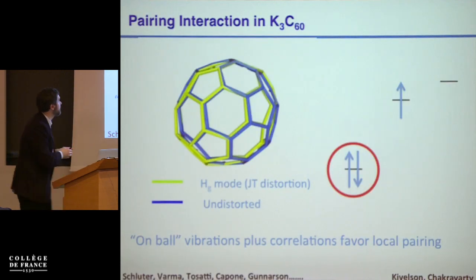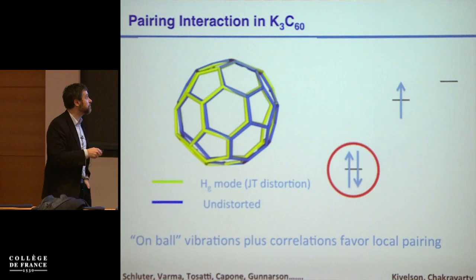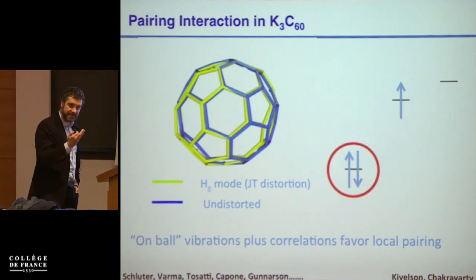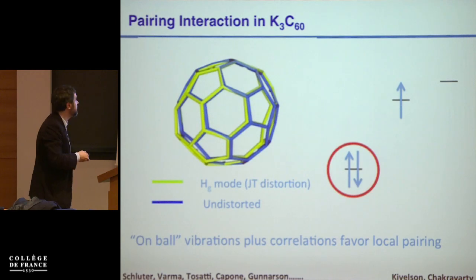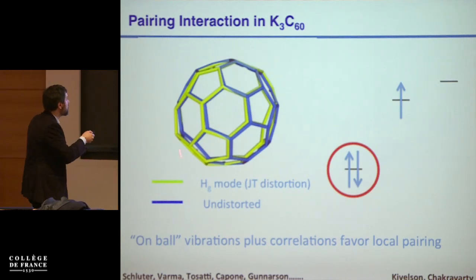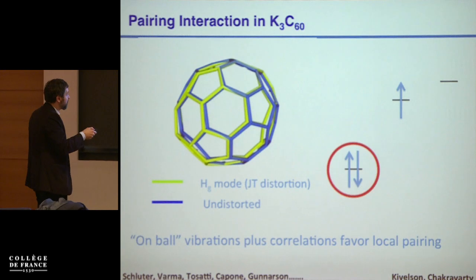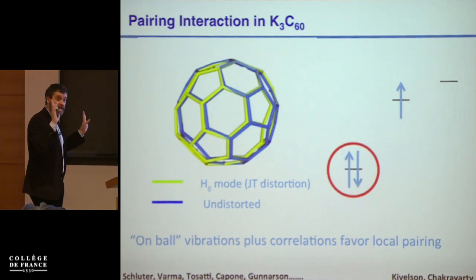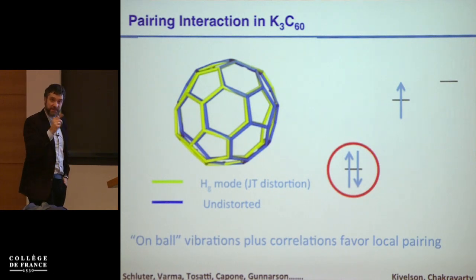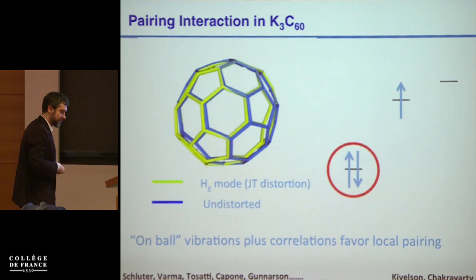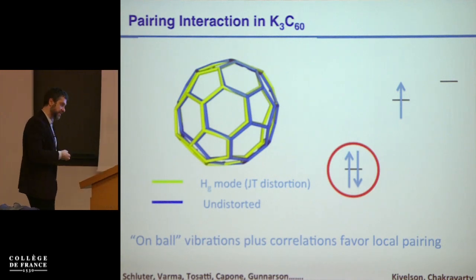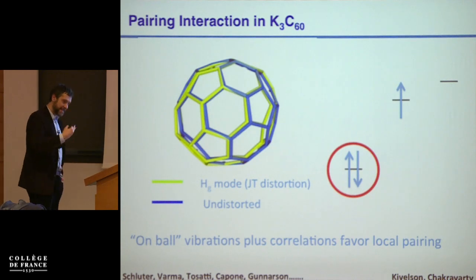And the reason why this happens, there's been a lot of discussion, but all I'm going to tell you is what has guided us through our experiments. And I will leave this a little bit up in the air at the end because this is being studied a lot. What is known is that on-ball vibrations, especially those of this five-fold degenerate Hg mode symmetry, are helpful in reducing a putative high spin state into the formation of singlets in one of those orbitals. Actually, one occupies 3 of these reduced orbitals that beat with one another and give rise to this type of superconducting state that more advanced theories have explained as a form of Jahn-Teller activated negative Hund's coupling.